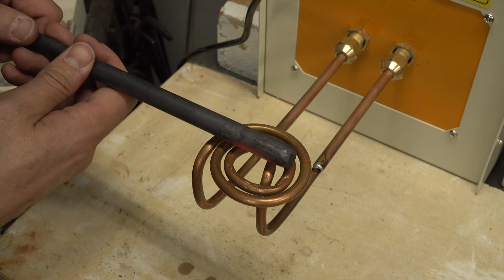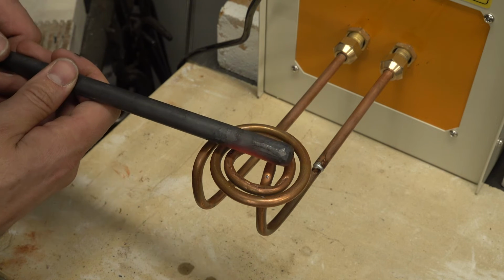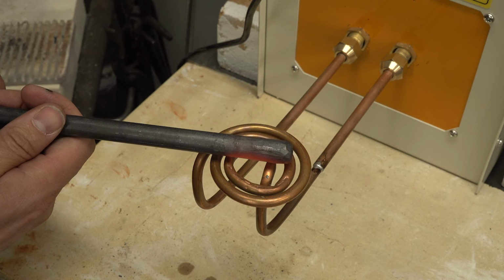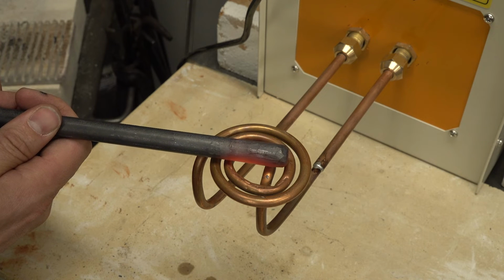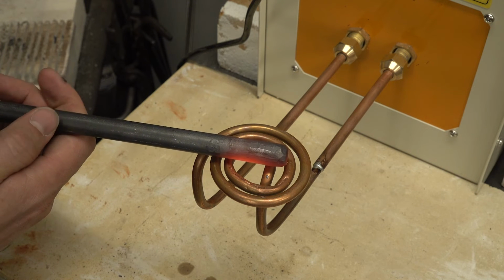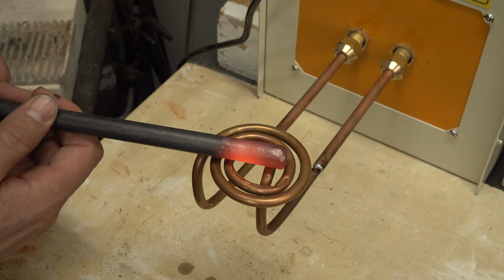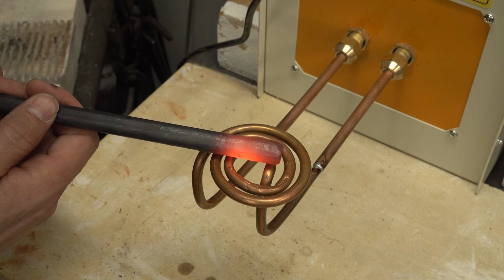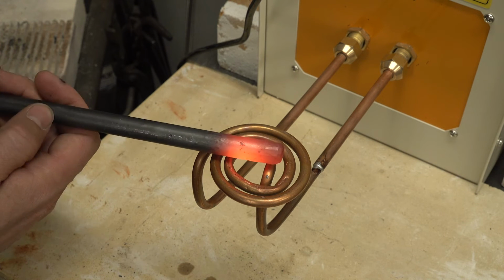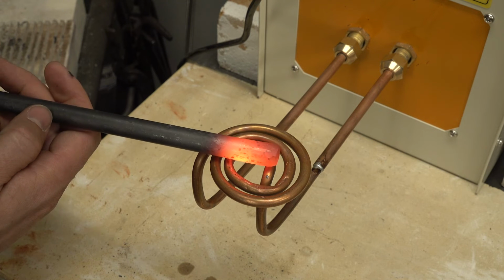You can see that with cylindrical stock, it takes quite a bit longer to heat the material up than with the helical coils. That being said, within a minute or so, it is up to a nice bright forging temperature, and I have gotten up to welding heats with this pancake coil.